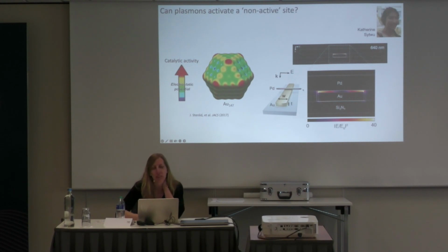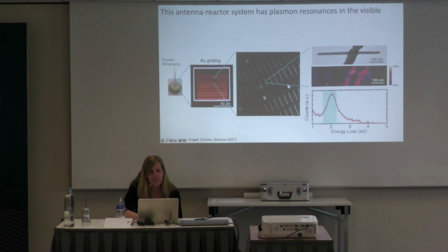To test that, we looked at this crossbar geometry where we had a gold bar that was basically our absorber, and now a palladium nanorod. And here in cross-section you can see the electromagnetic hotspot is basically between the gold and the palladium. I showed you earlier that hydrogen always wants to leave and enter from the tips of the palladium nanorod. But with this electromagnetic hotspot, we wondered if we could get palladium to leave or enter by the faces of the nanorod where we had this hotspot.